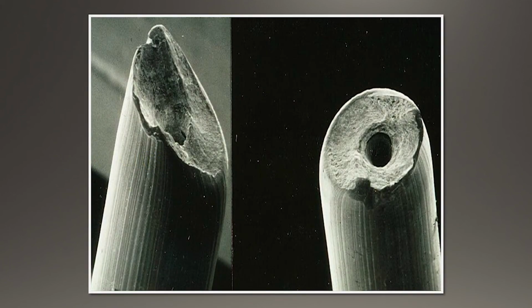Well, this turns out to be a sample. These are both ends of the break, and there's a hole in the middle of both samples. There's a little bit of ductility, so slight reduction over here. And this is caused by a casting problem in the rod called macro porosity. That usually occurs in the last portion of the metal for solidification to take place, so it's almost always in the center of the cast bar. If it's too big and doesn't get eliminated during hot rolling or wire drawing, there'll still be a void present, and it will cause that wire break. So again, this is a casting-related issue.